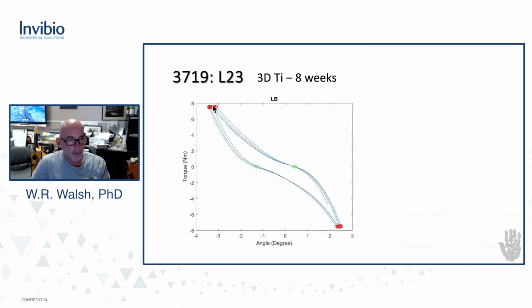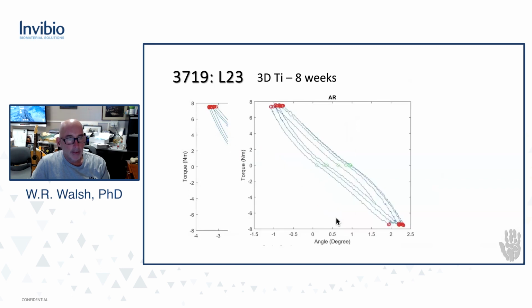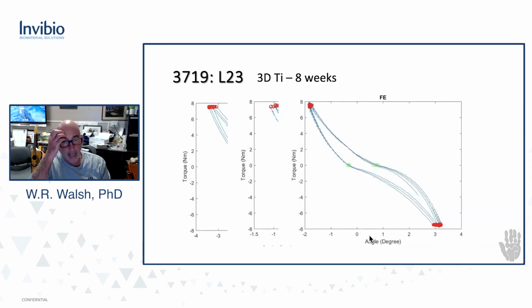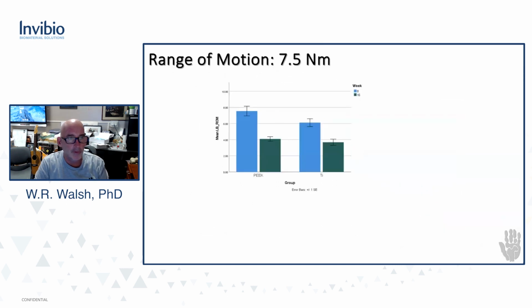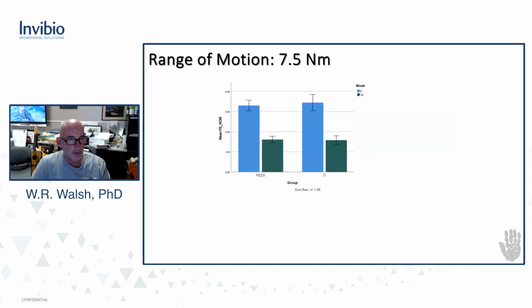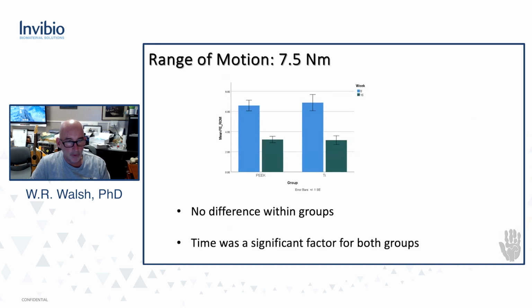We analyzed the range of motion going to the left and going to the right. Same thing with axial rotation. So don't forget, these are very small in axial rotation, and flexion extension. So this is an example of a 3D Ti at 8 weeks, nice and fused. So when we summarize that data and we do lateral bending, again, 8 and 16 weeks, there's a progression for both implants to progress to fusion, getting more stable. And there are no statistical differences either in lateral bending, flexion extension, or axial rotation. They both progress with time, and there are no differences within the groups, but time was a significant factor.